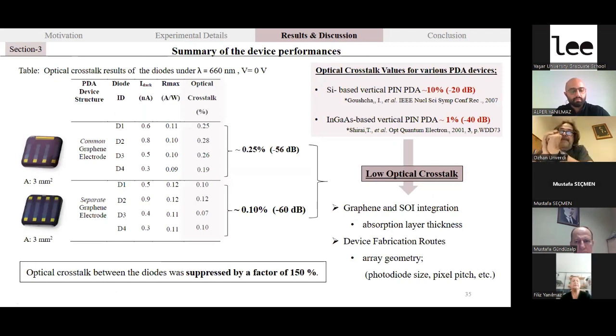When I summarize and compare the common graphene electrode and the separate individual graphene electrode, we observed the suppression of nearly 150% optical crosstalk between the diodes. When compared with the literature, different fabrication routes or designs can be applied, but the published value is nearly 10% for the silicon case and nearly 1% for the indium gallium arsenide based photodetector array. Even when we consider these results, our detectors, even under self-powered condition, show excellent performance and also the lowest optical crosstalk value.